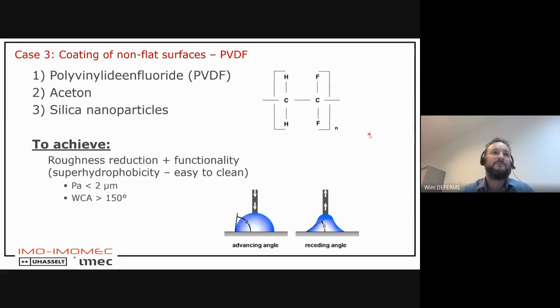So what we did, we started with PVDF in acetone, and later we also added nanoparticles. So it's not a purely polymer-based material, but a hybrid material, a hybrid ink, where we use polymers and nanoparticles to optimize the roughness, but also to add functionality. And the functionality we added using these nanoparticles is superhydrophobicity. So that's something that we investigated.